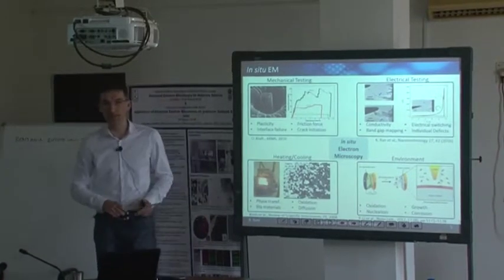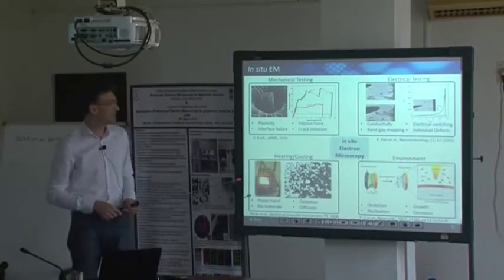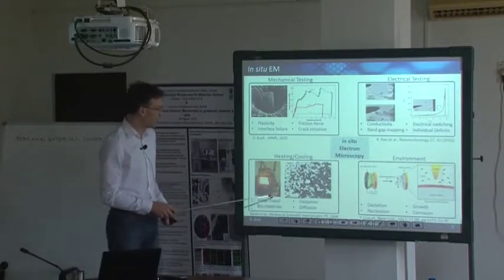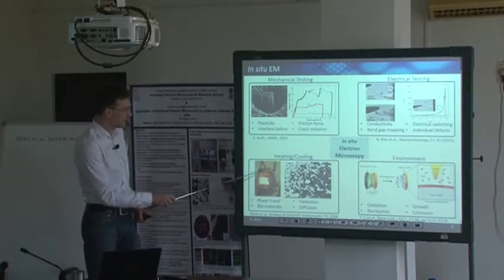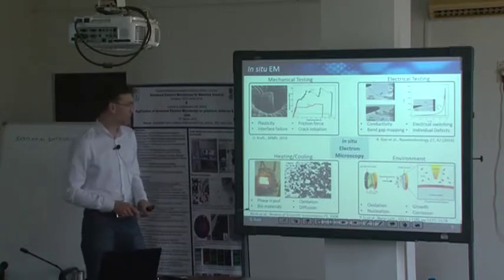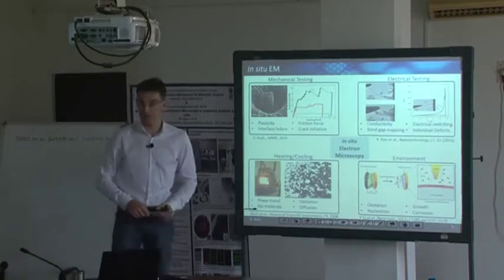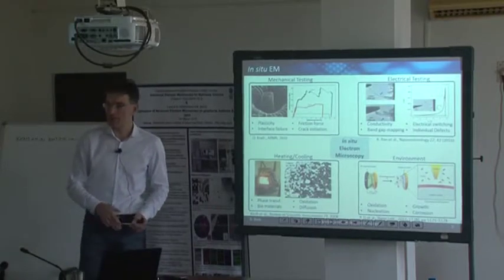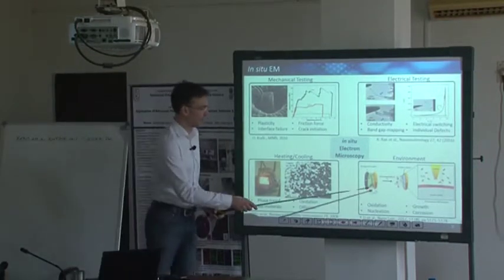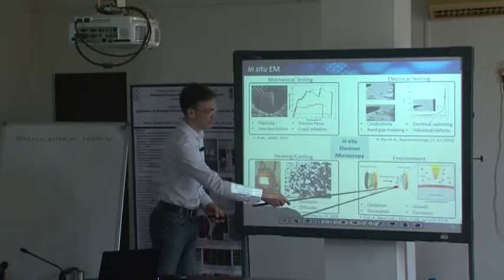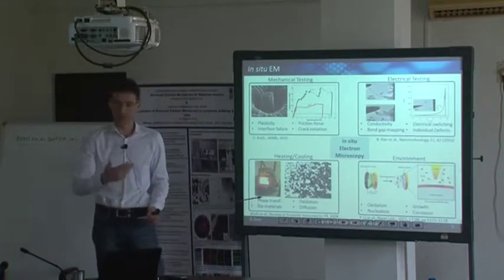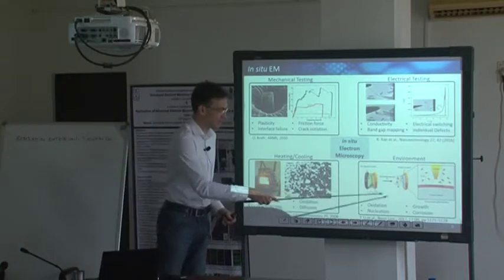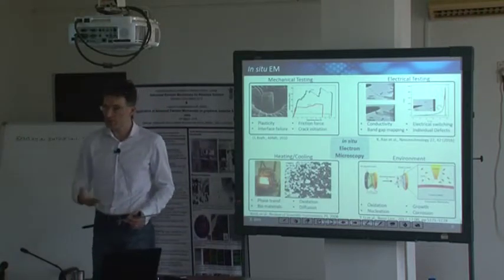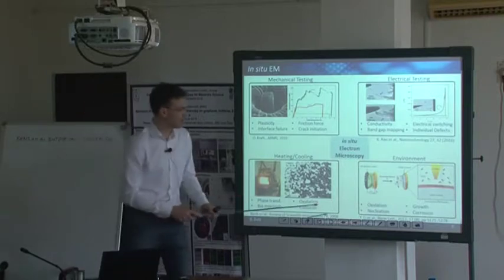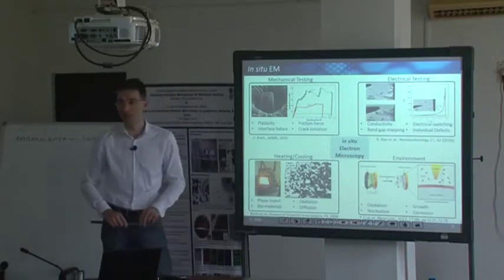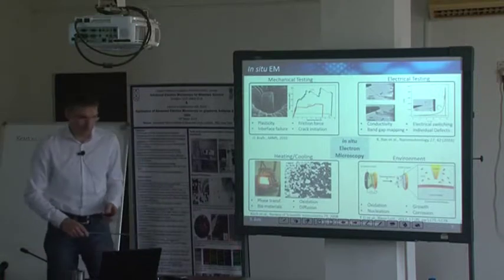And here's an example. I will show that later, where we use a very specialized tool that will bias materials in a transmission electron microscope. This is such a heating stage here, so people heat quite a lot, I would say. This is an example of recrystallization in the scanning electron microscope. And you already saw this example of plating and the generation of lithium tubes, meaning this is a more operando experiment where we run a battery within the transmission electron microscope to study the oxidation behavior of pure lithium metal. So this is just an overview.